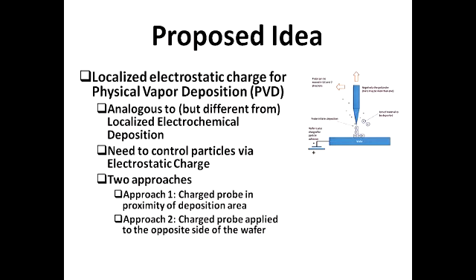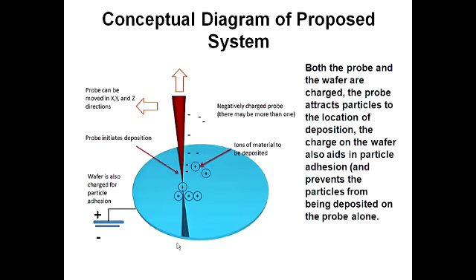If we want to have deposition on one side, we use the probe on the opposite side of the wafer, not on that side. As you can see in this figure, this is our wafer. We charge that, and also this is our probe. We could change the position of the probe in X, Y, and Z direction. We charge the probe negatively. Maybe we have not only one probe, we could have two or more. That depends on our application. And also the wafer is charged to increase the particle adhesion. Both the probe and wafer are charged. The probe attracts particles to the location of the deposition, and the charge on the wafer helps particle adhesion, and also prevents the particles from being deposited on the probe.